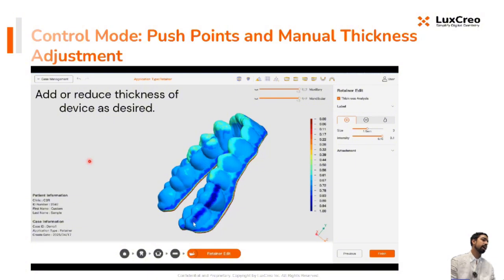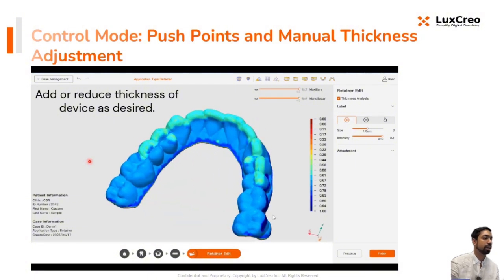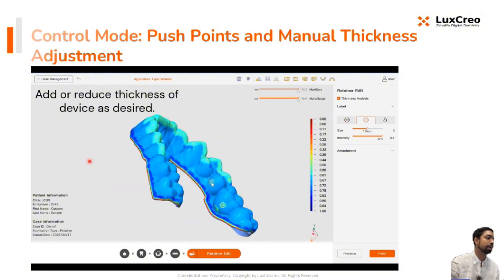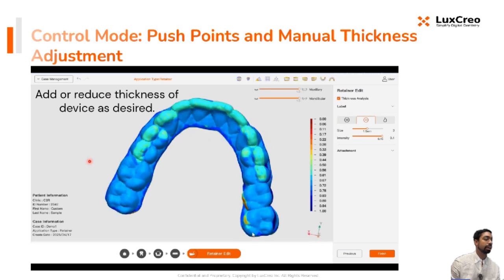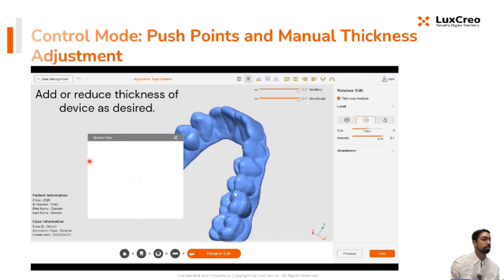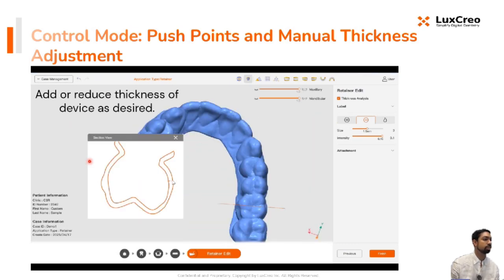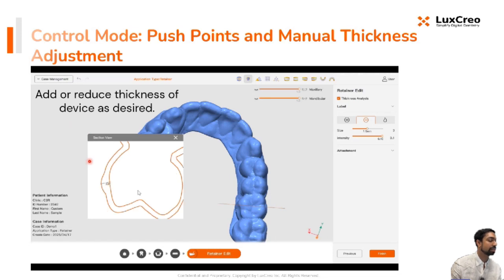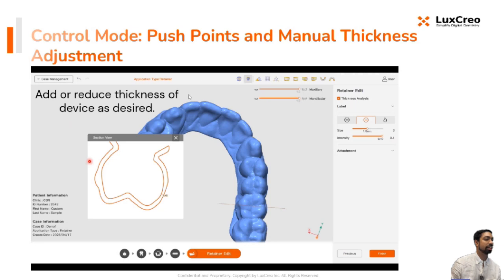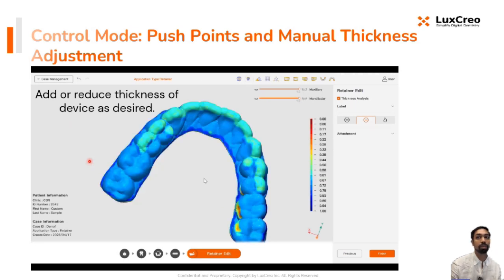You're also able to add or reduce the thickness of the device. You can see here we're able to create a thickness analysis heat map. Then by pressing plus or minus or the smooth tool, you can add or remove thickness, and you can see what that thickness is. It's a nominal thickness of 0.7, but in those areas you can see 1.2 and 0.4, where I added thickness and removed thickness. And that allows you to create even more customization for a bespoke device.